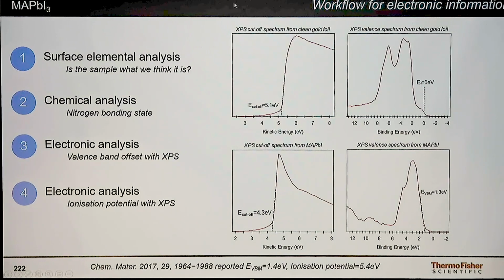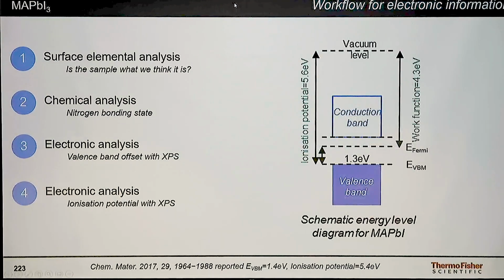So again, we're not just determining the chemistry using XPS, we're able to get further information about the electronic properties of the material as well. And there, just to get the schematic energy diagram there. So by measuring where that valence band maximum is and knowing the position of the vacuum level, we can then calculate the ionization potential and the work function of the material.